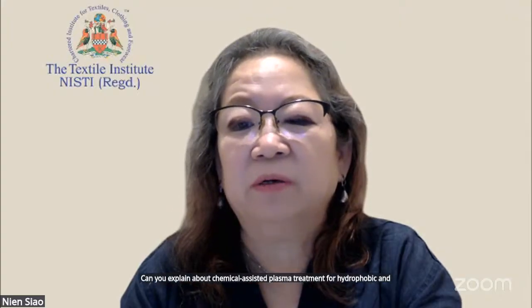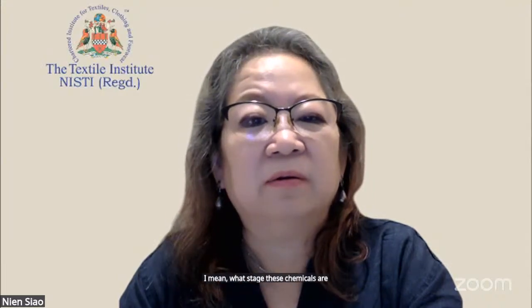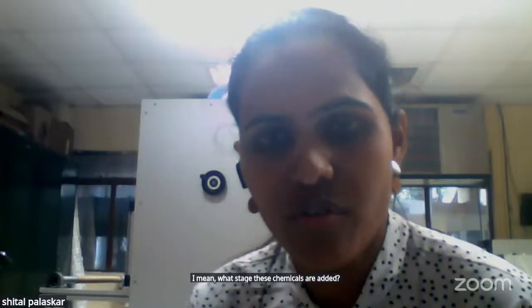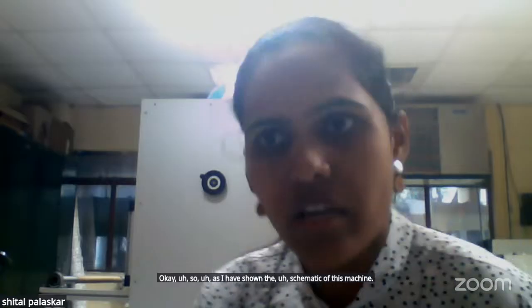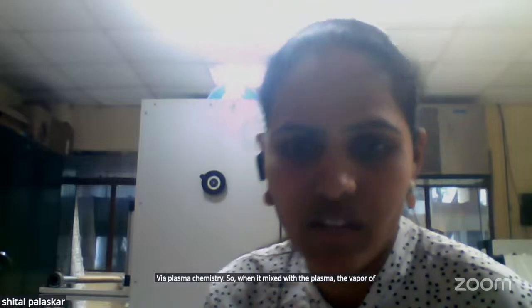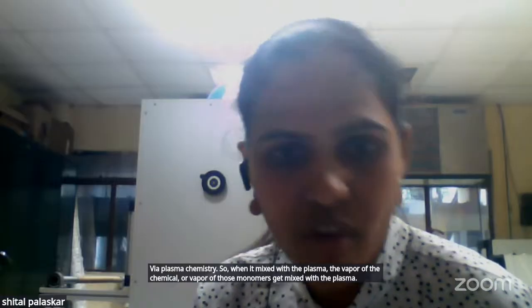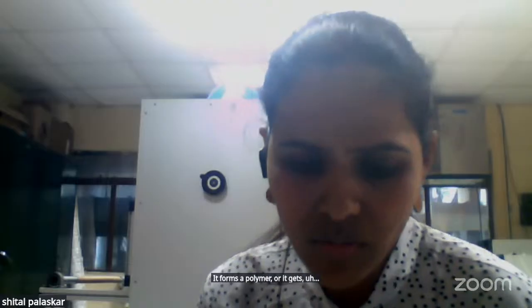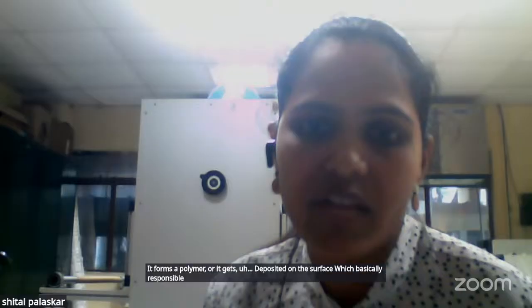Right. Mr. Sandeep Kaswan has a question for you. Can you explain chemical assisted plasma treatment for hydrophobic and flame retardant finishes? At what stage are these chemicals added? Okay, as I have shown in the schematic of this machine, there is a provision to introduce the monomer in vapor phase. That is called plasma enhanced chemical vapor deposition. So we introduce the monomers in a vapor form, which gets deposited onto the surface via plasma chemistry. When the vapor of those monomers mixes with the plasma, it forms a polymer and gets deposited on the surface, which is basically responsible for giving that functional finish, like water repellent, antimicrobial, flame retardant, and many others.